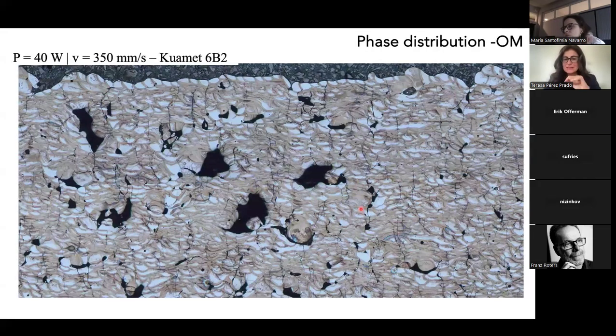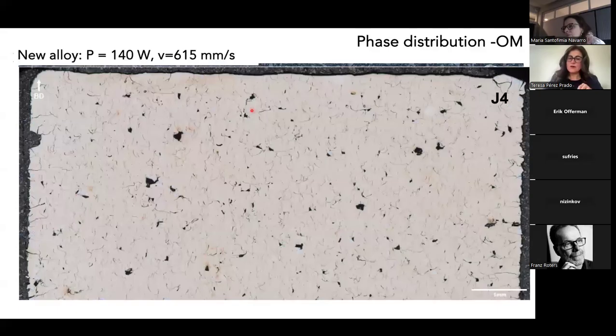I bring back a slide that I showed you before of the commercial alloy, how the composite structure looked. We did the same with the new alloy, processed within the processability window. Within all this processability window, we polished the samples, we etched them, and at least within this etching method, we couldn't reveal crystalline regions. Let us zoom in a bit. But the crack problem is still there, as you can see. But this was looking good.